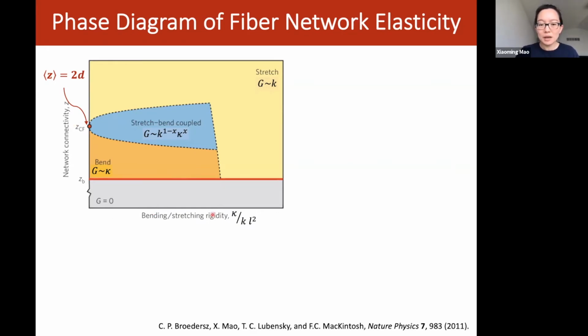So in the limit where bending versus stretching goes to 0, you are in the central force, bead and spring model limit. And in this limit, the network only has rigidity above this central force isostatic point, which is the rigidity percolation point of the lattice models we study. Above this point, the network has rigidity even if it only has central force interactions. So the elastic modulus is proportional to the stretching stiffness of the fibers.